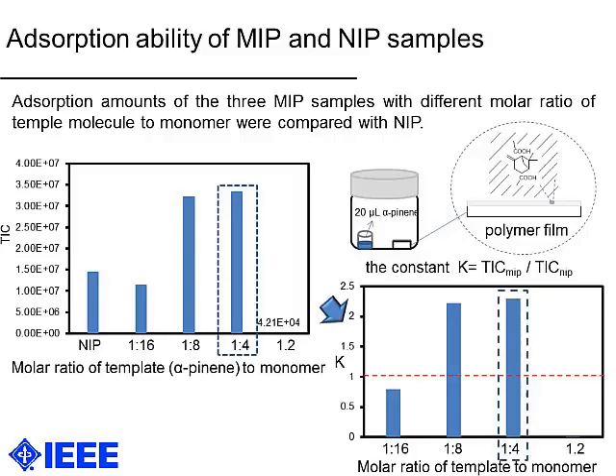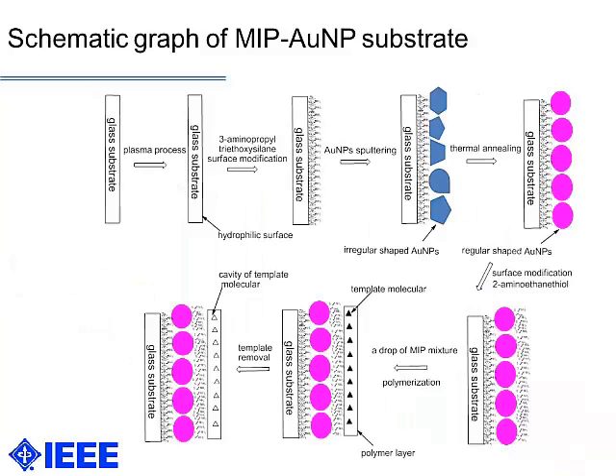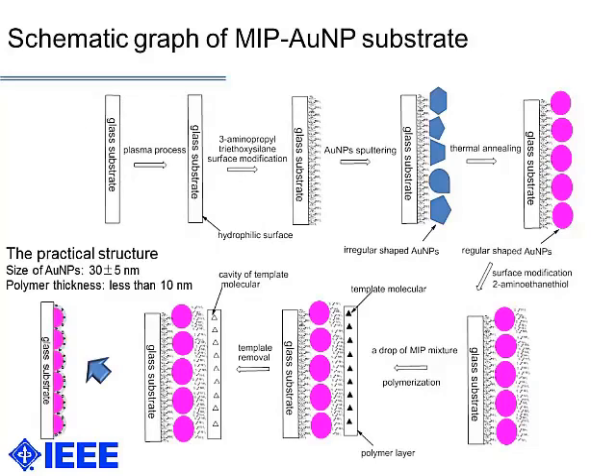And then we used different molar ratios of template alpha-pinene to monomers and compared with NIPs. And here, the molar ratio 1 to 4 has the best absorption ability. And also we compared the K value, and the 1 to 4 molar ratio of template to monomer shows the best selectivity result. And then this is a schematic diagram of the MIP AuNPs substrate shown like this one. And the practical structure is shown like this. The size of the AuNPs is thought to be about 30 nanometers, and the polymer thickness is less than 10 nanometers.